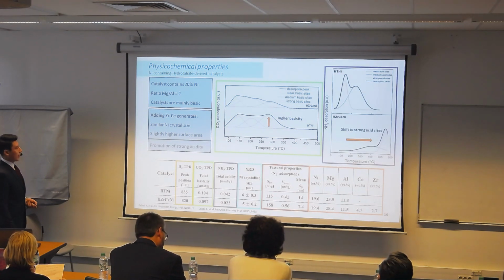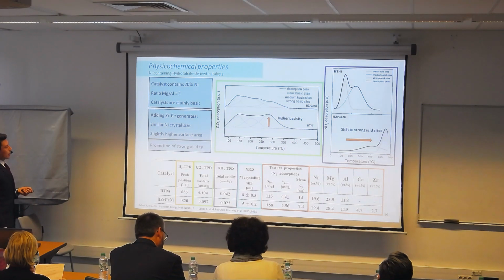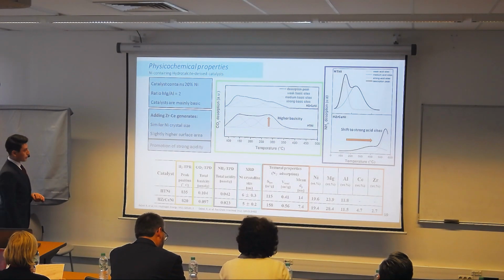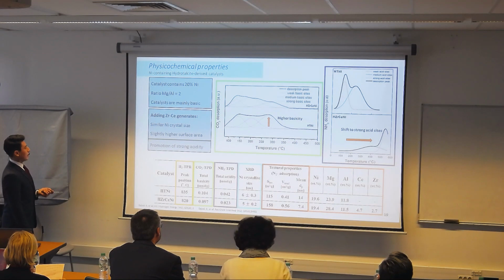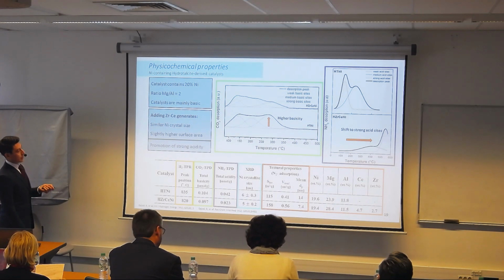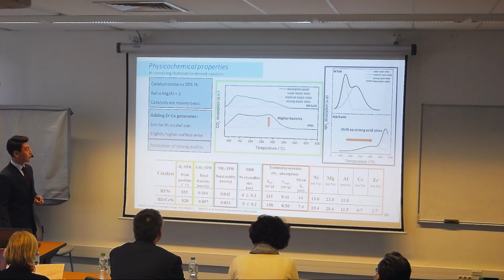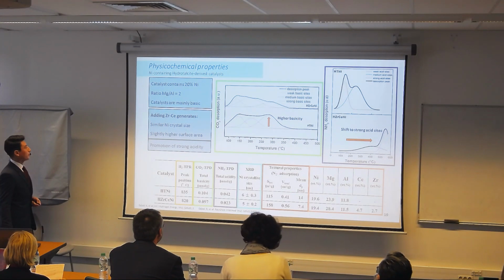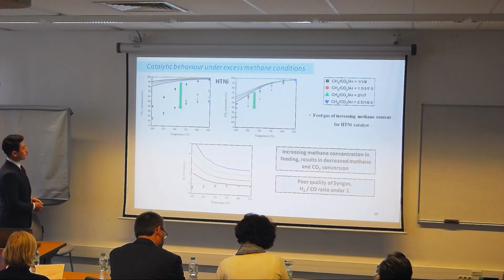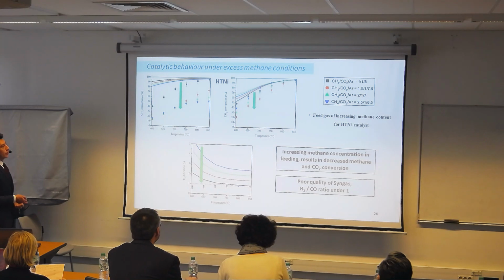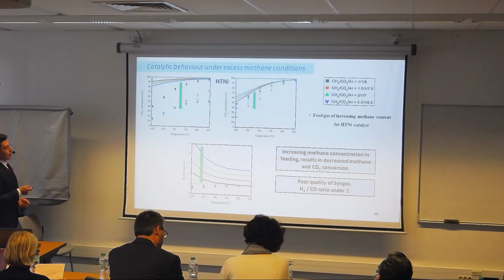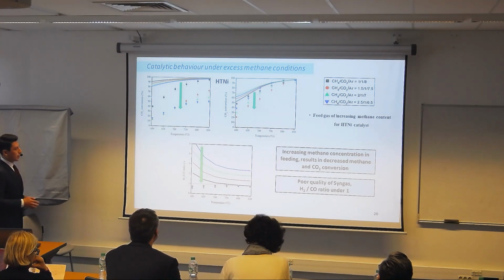Talking about the acidity, when we introduce the promoter, we have a promotion of the strong acidity. You can see here we are moving onto the strong acid sites, and we also have an increase of the surface area. So we went straight to test what is happening when we increase the concentration of methane in the sample.